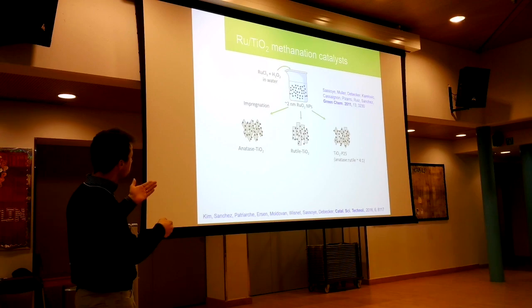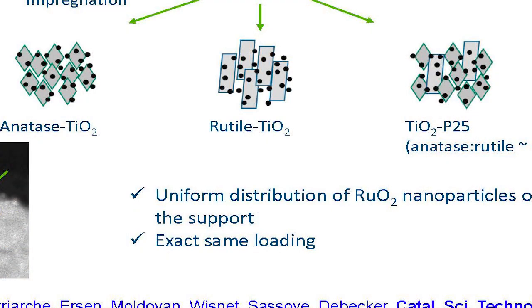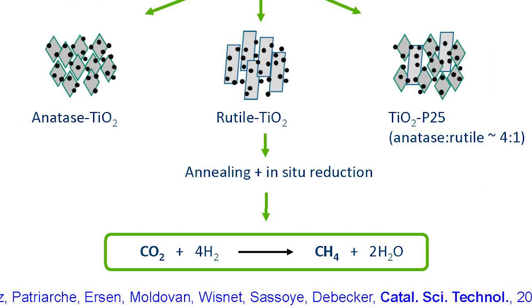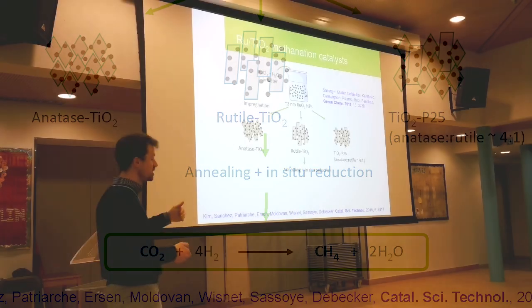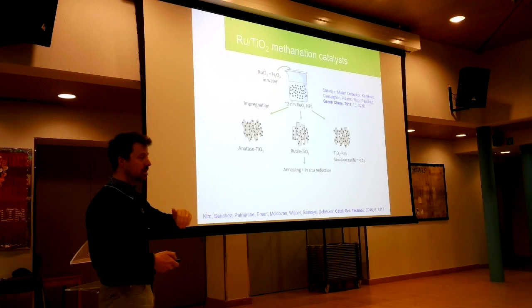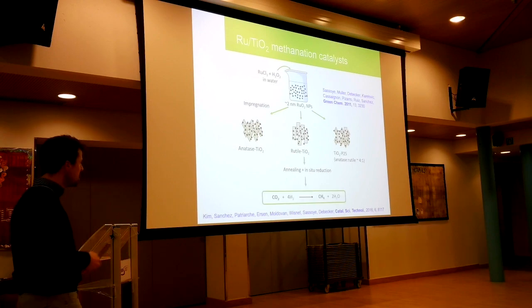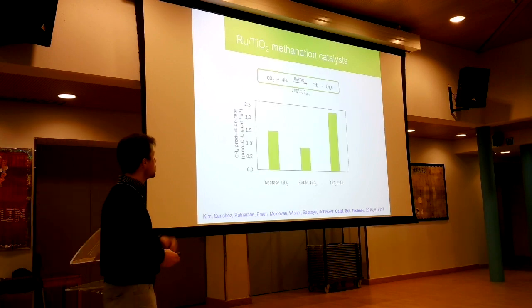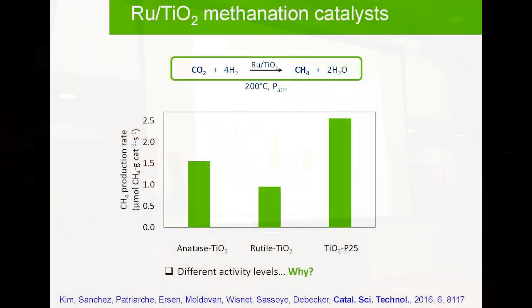Once you do this kind of impregnation, you still have to do a kind of calcination and then an in situ reduction, because what is active in the end is not ruthenia, but ruthenium, so the metallic ruthenium. And then we test them in the reaction. So this is what we found when we tested those three systems.